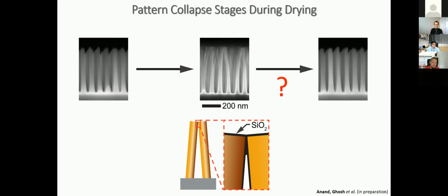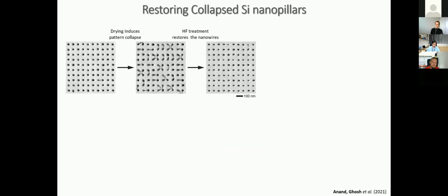Well, one thing to note: when two silicon surfaces come together, they always have a native surface, which is usually the native oxide layer. So this native oxide surface, when it comes together, is the thing that sticks, right? So it's adhesion between the oxide. So the question is, if I want to release them, it's about disrupting the adhesion between the oxide surfaces. How can one break the bond between oxide? So what removes the oxide? It's HF, right? Any of you who've done microfabrication know that if you want to remove native or any oxide, you put it in the HF or buffered oxide etch. And we've tried this, and actually it works. So you see here when you have damaged structures, you etch them in the oxide, and almost all of them restore.